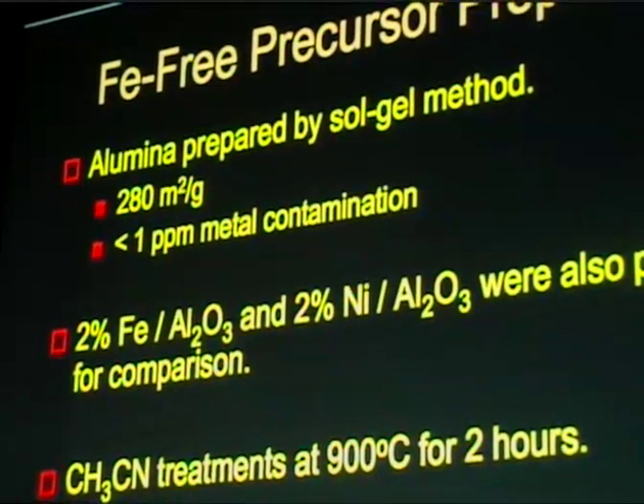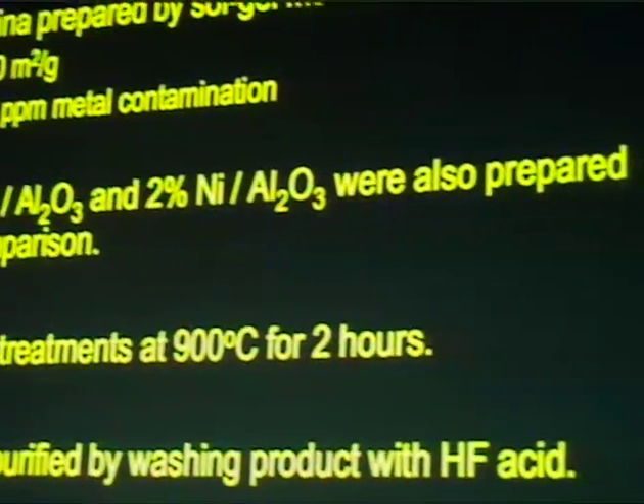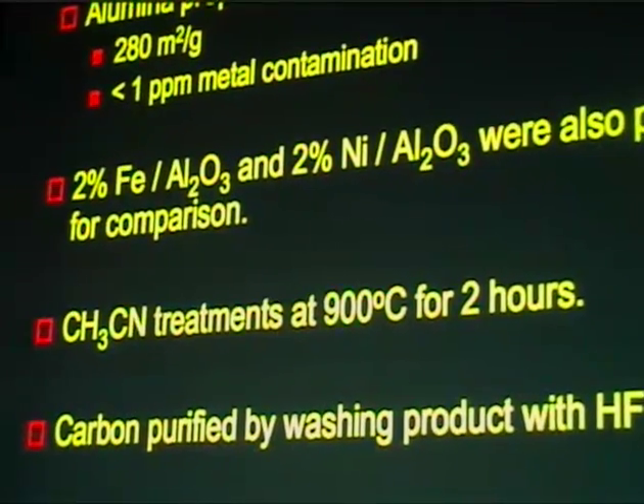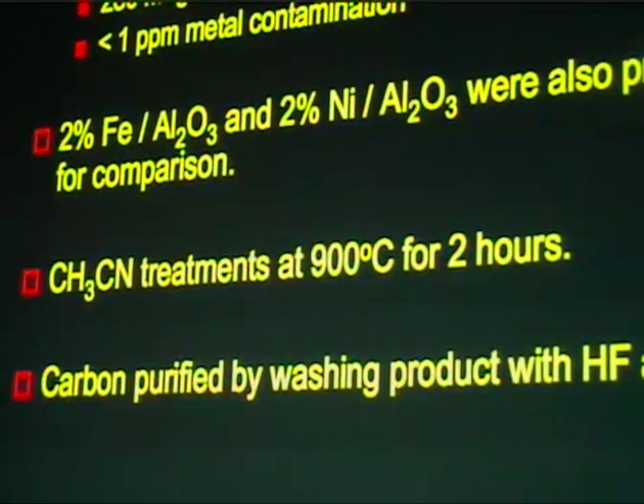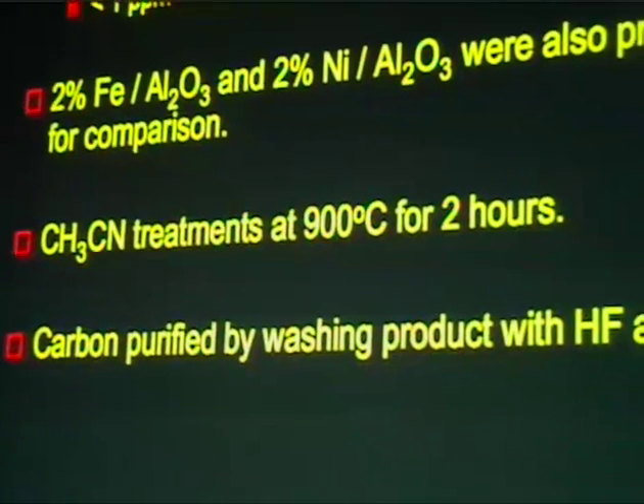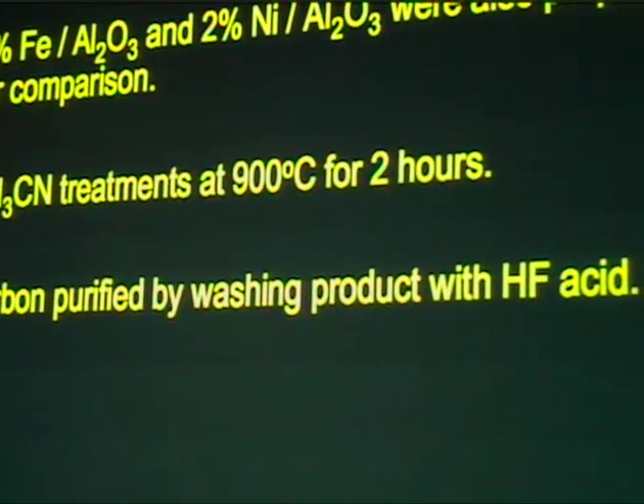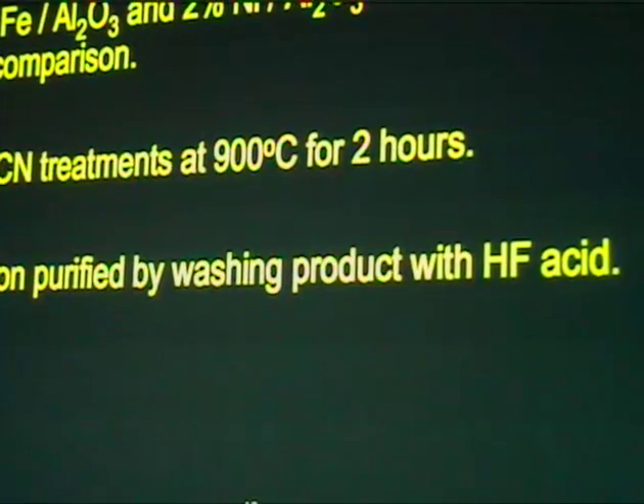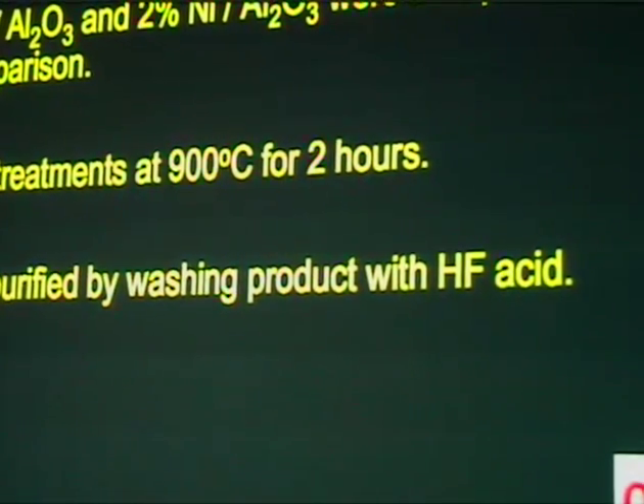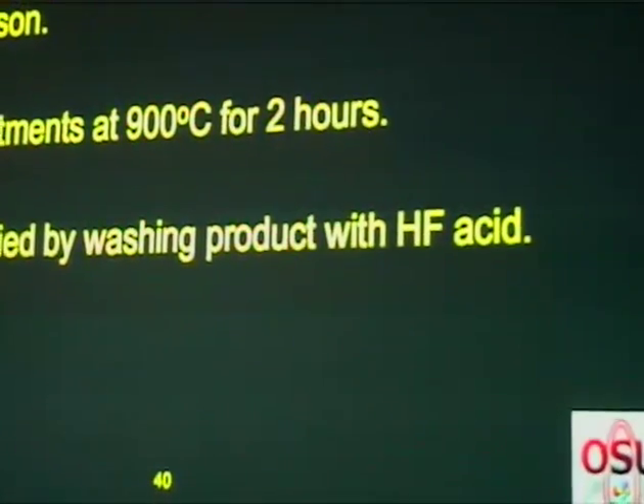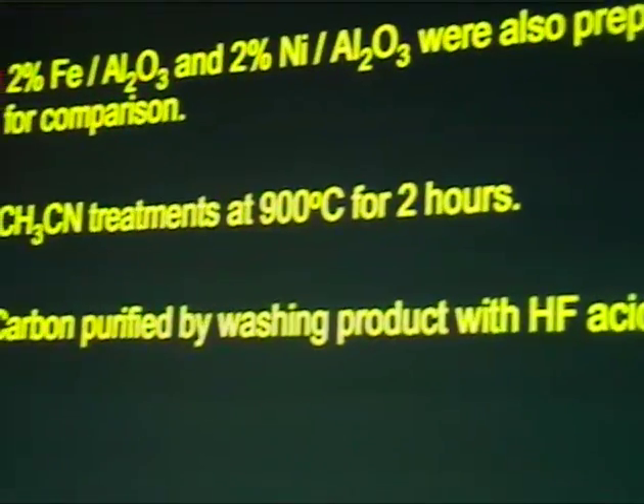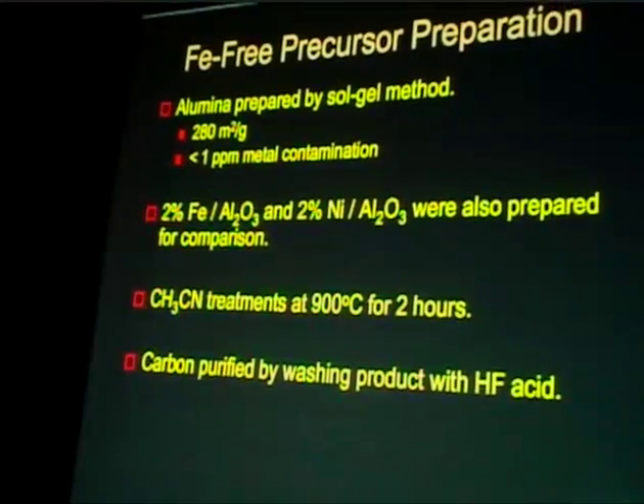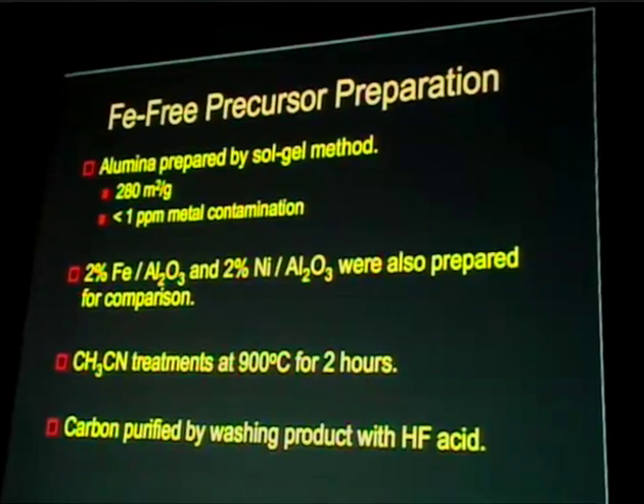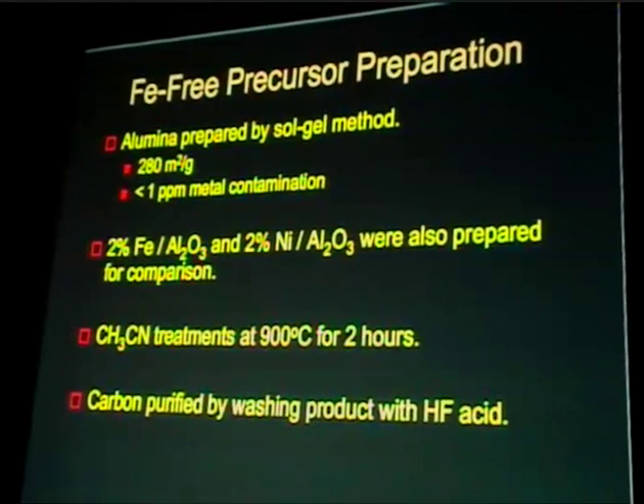Because although even the Vulcan carbon, which didn't have any iron, showed significant activity after acetonitrile pyrolysis, Vulcan carbon still has some impurities in the form of iron, about 70 ppm. So we really couldn't be sure. So we said, well, let's try to prepare some support which would be really free of any metal contamination.